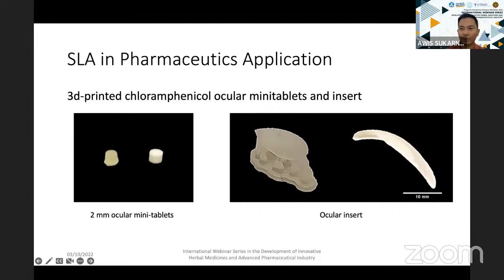This is quite common in laser printing, especially if you prepare it using your own resin, because at this point it is basically at the surface of the platform. Compared to the resin that you buy from the market, which normally shows a very sharp edge, this one has chloramphenicol, and this drug slightly interferes with the photopolymerization process. That's why you get this kind of skirt here.